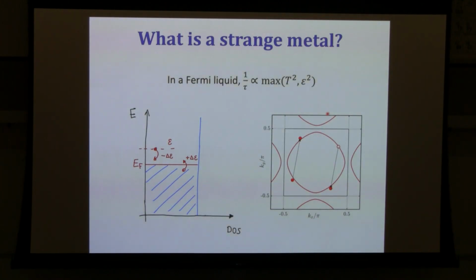Okay, so what's the source of this behavior? First, I wanted to discuss a little bit what is causing the T squared behavior of the scattering rate in a Fermi liquid. Okay, so that's the conventional behavior. Where is that coming from? So the statement is the following: in a Fermi liquid, if we have a Fermi surface, the low energy excitations of the system correspond to exciting a single particle or a single hole to an energy which is close to the Fermi surface, say some energy epsilon away from the Fermi energy. And the statement is, once we excite this extra particle, this particle is not an exact eigenstate of the system, so it would decay. Okay, and the rate at which it decays scales quadratically with the energy of that particle relative to the Fermi energy.